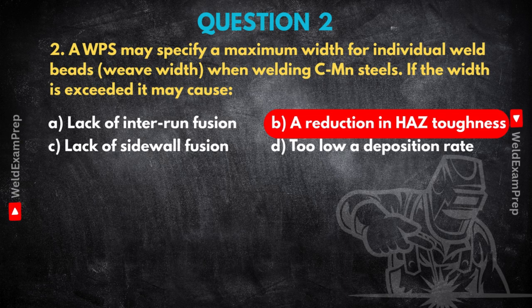When you use a very wide weave, you're putting a lot more heat into that area per pass, higher heat input. And for CMN steels, too much heat, held for too long in that HAZ, can cause the microscopic grain structure to grow larger, become coarser. Think of it like wood grain. Fine grain is strong and tough. Coarse grain can be more brittle.